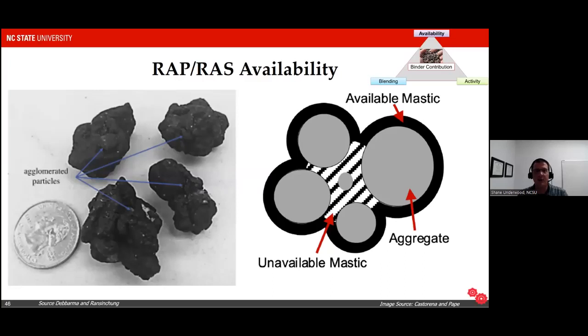But in fact, within RAP, there are these agglomerations. Now, these agglomerations actually are very stiff. It's almost impossible to break them apart with your fingers. And because of that, those agglomerations hold all of the binder inside and make it unavailable to mix with the asphalt concrete mixture. And that's demonstrated in the schematic here. So we've got the surface asphalt that's available, but then we've got this internal section which is completely unavailable and not mixing with the asphalt concrete.